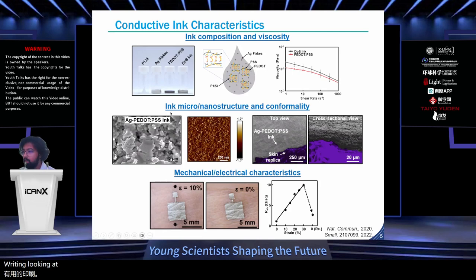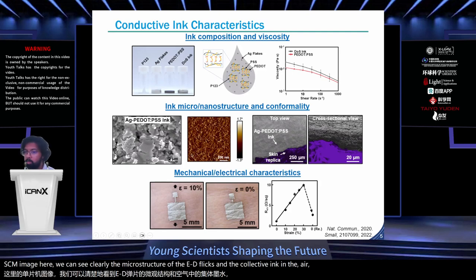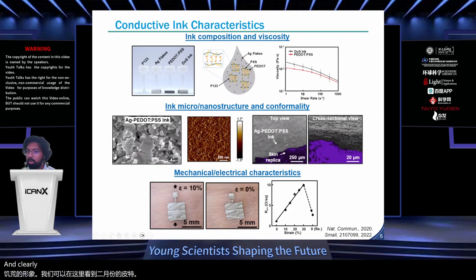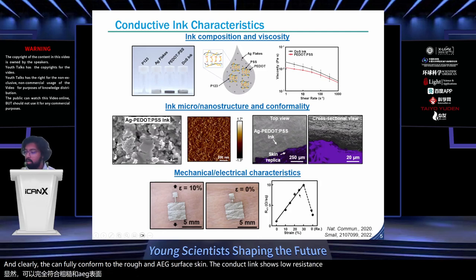Looking at the micro and nanostructure in the SEM image here, we can see clearly the microstructure of the Ag flakes in the conductive ink. In the AFM image, we can actually see nanofibrils of the PSS. And clearly, the ink can fully conform to the rough and irregular surface of the skin. And the conductive ink shows low resistance, even when it is stretched.